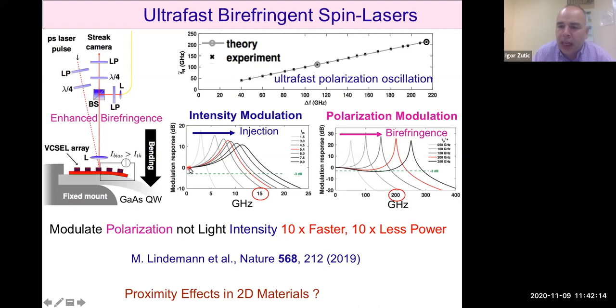So you need to go to 10 times higher injection current to reach this value, as opposed to being at a much lower injection. However, in a spin laser, relying on high birefringence, one can stay at the low power of injection, and by increasing birefringence, one can effectively increase the resonant frequency 10 times higher than the maximum value in the best semiconductor lasers. In other words, we can change polarization much faster and also at much lower energy than we can change the intensity of emitted light. And the polarization that comes out is connected to the imbalance between spin up and spin down.